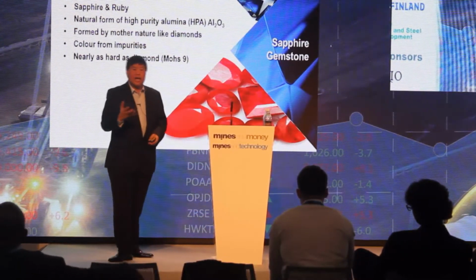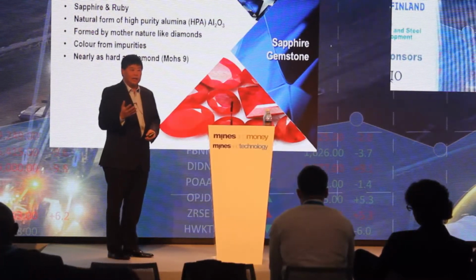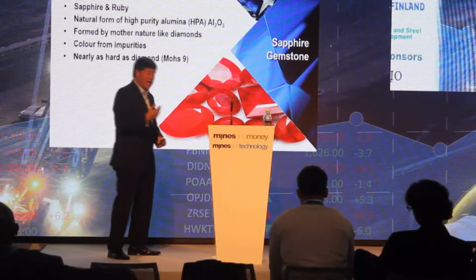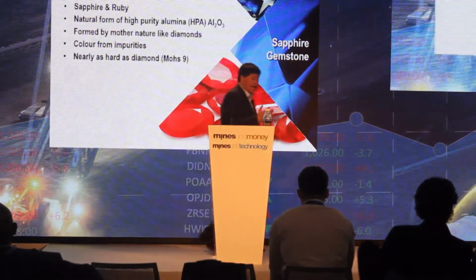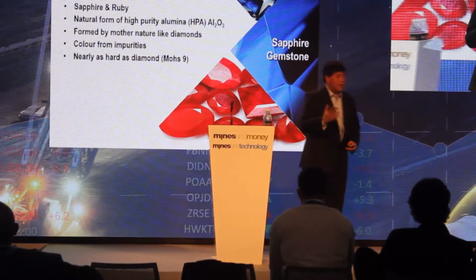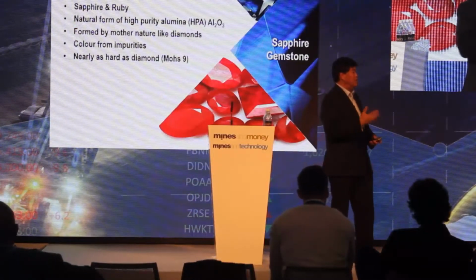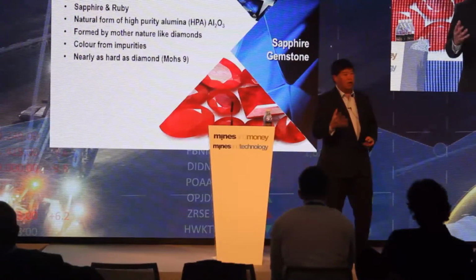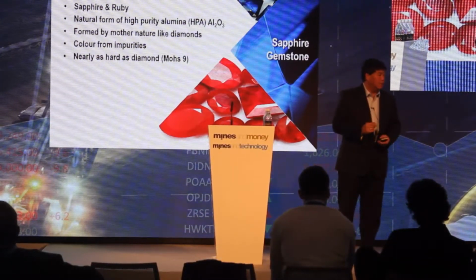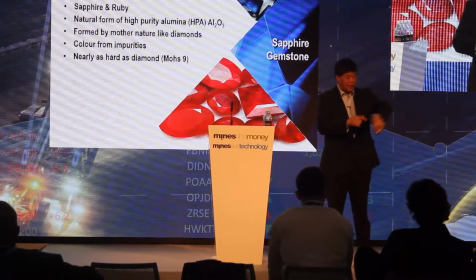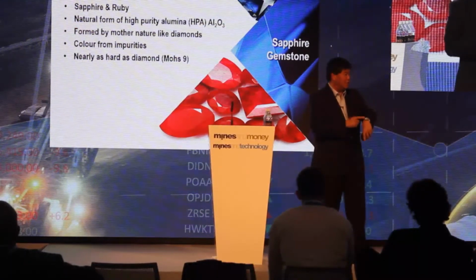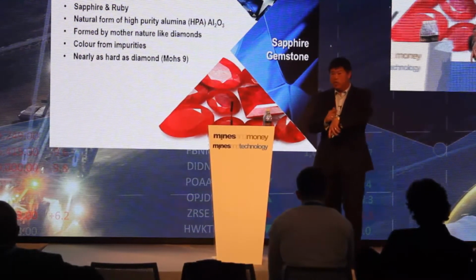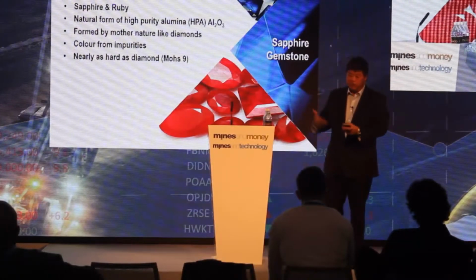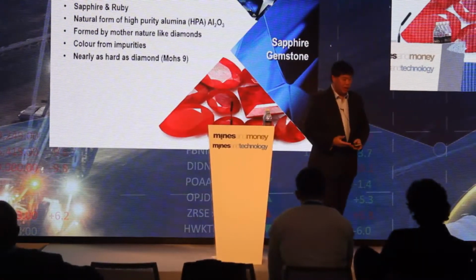Now, sapphire has a hardness index of 9 compared to diamond, which has a hardness index of 10, so nearly as hard as diamond. And the only reason the colour of sapphire is blue is because of impurities like iron and chromium in the alumina that creates the blue colour. But today, if you want to make synthetic sapphire for your watch face, you don't actually want a blue tinge on your watch. So you actually have to start off with a high purity alumina.